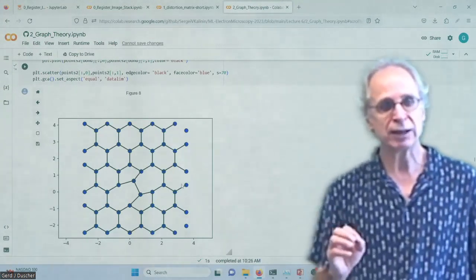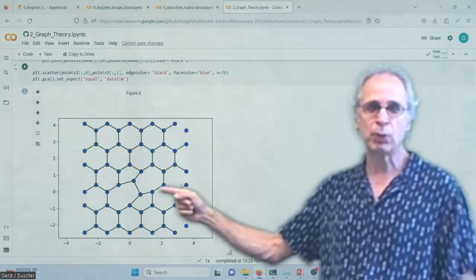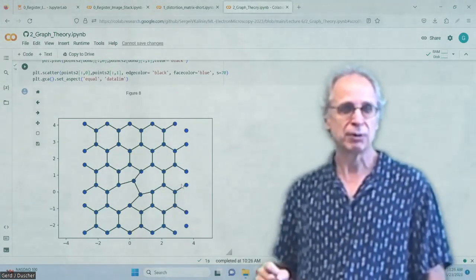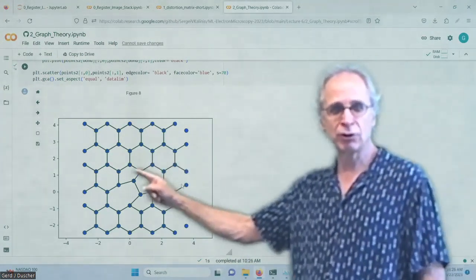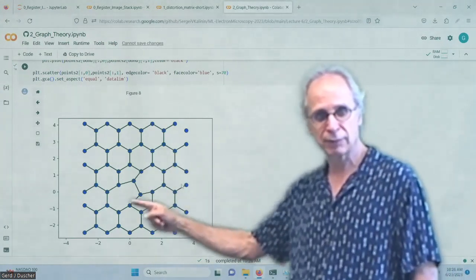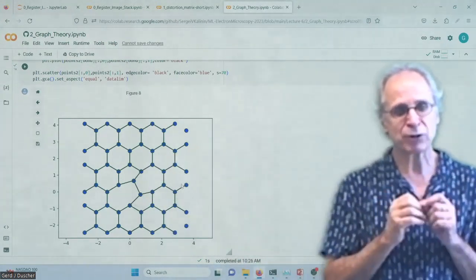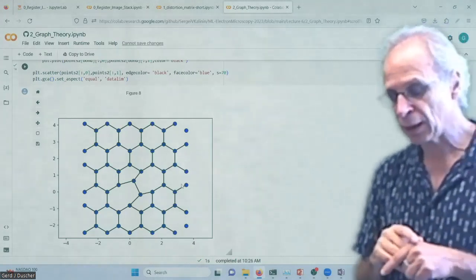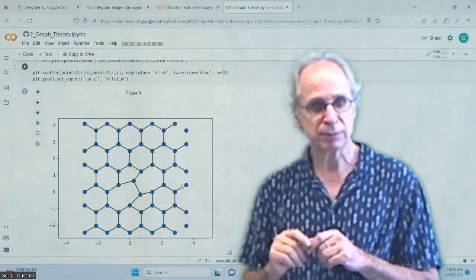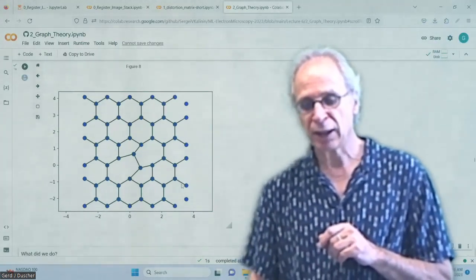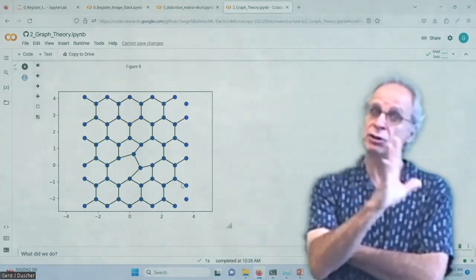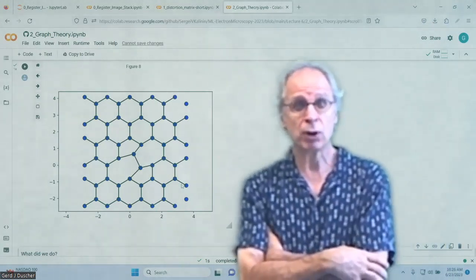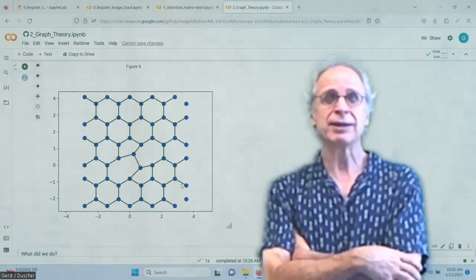And then I actually get the reliable bonds for that as well, because bonds are around the convex ring here. That must be my bonds in the projection, right? And so this is now a way in 2D or 3D to get bonds independently of how far away your atoms are.